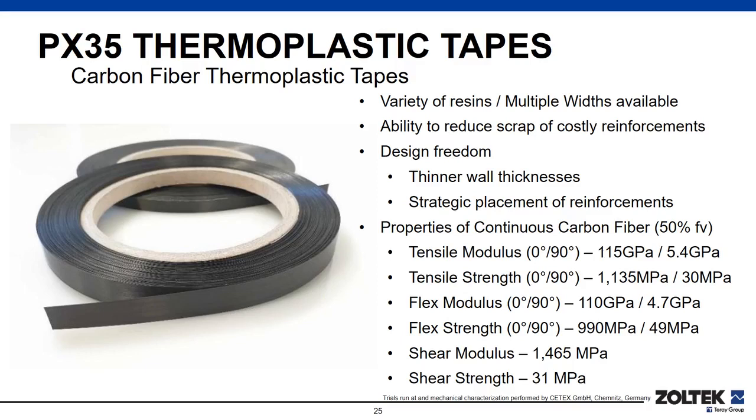All of these properties are based on a 50% fiber volume loading in nylon resins. However, the properties can be tailored based upon the weight fraction, which can vary as low as 30% and go as high as 65 to 70%, depending on the resin systems and the flow properties of that base resin, and the suppliers of the carbon fiber reinforced tape.